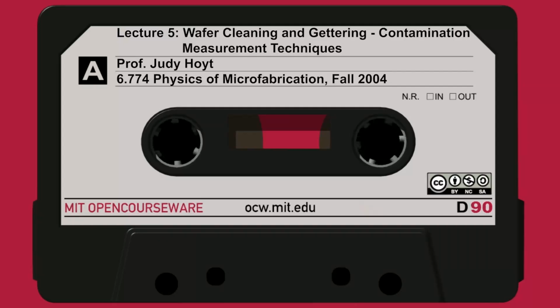It also can give you information about the profile in depth, and that's kind of nice. If we go back a couple slides to slide 10, what happens is you collect these ions as they come off, and you measure them as a function of time. In the first couple seconds, you sputter off the first few monolayers. The second few seconds, you sputter deeper. So as you're constantly sputtering the surface off at a constant rate, and you're measuring what comes off as a function of time, you know pretty much exactly what depth those ions came from. So if you want to sputter a little deeper, you can get some information about the profile.